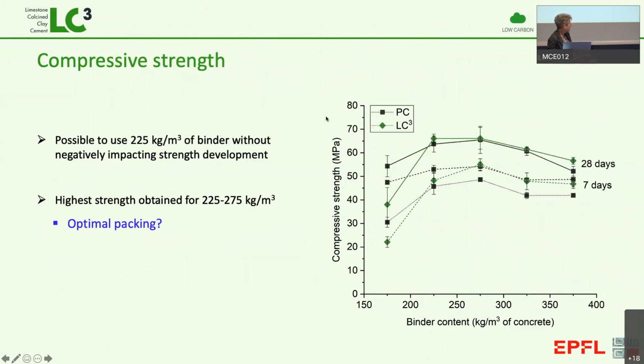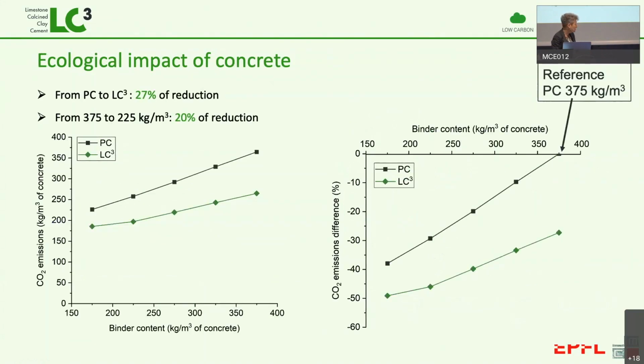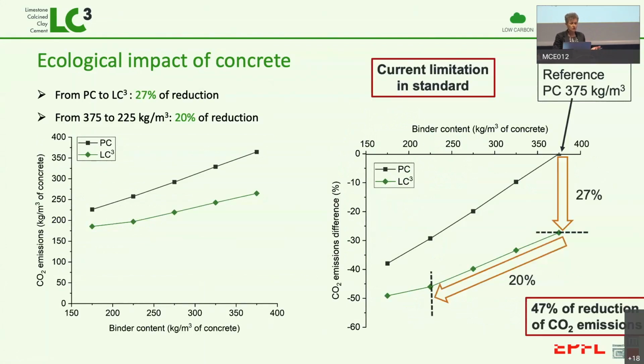And in terms of strength, the strength's actually better when we have a lower cement content. You'll have less problems of overheating. You'll have less problems of shrinkage and cracking. And then if we look at all of this in terms of CO2 savings, you can see you can save as much by working at the concrete level as you can by working on your cement itself. So this is a very simple thing. People say, well, you have to use more admixture, but the price of the extra admixture was way more than compensated by the amount of cement you saved.